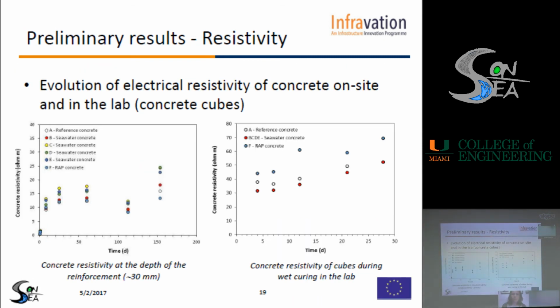These are the results of the resistivity, the electrical resistivity of concrete, on the left on-site, and on the right on the concrete cubes in the laboratory. On-site, we can see that there are some variations in the resistivity, and in particular, we can see that the resistivity of the reference concrete and the RAP concrete were more or less always lower compared to the resistivity of seawater concrete. And this is quite strange because the contamination with chloride is expected to decrease the resistivity.